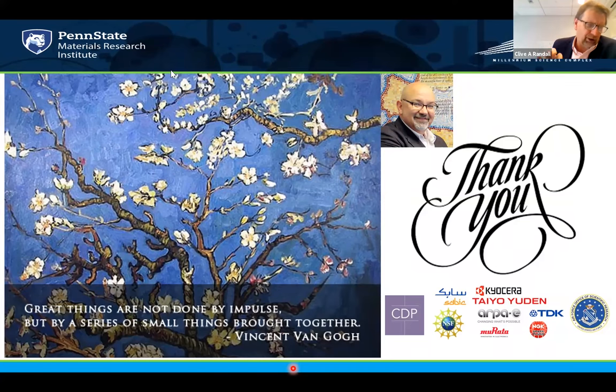I would recommend, if you've got good dispersion of nanoparticles, that's a good place to start, because you already have a strong driving force for sintering and you already have a high surface area to drive the dissolution step. But if you work on a system that easily goes into solution, even a water-based material, then you could work with 5 micrometer powders. So it's very dependent upon the system, but you can work around the volume fractions of liquid and everything else, thinking about the surface and the surface area.